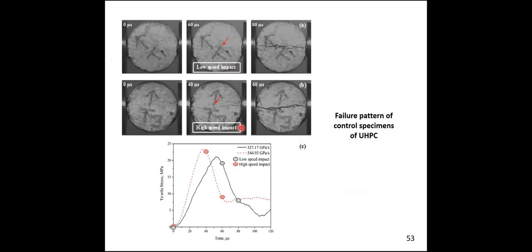So basically, we used ultra high performance concrete. Concrete was used in the study, and we wanted to understand the high strain rate behavior of this concrete. You could see, again we used DIC, digital image correlation technique. You could see the photographs at different time steps.